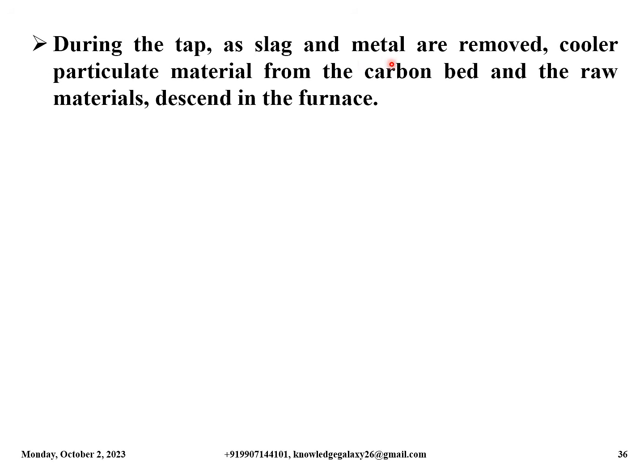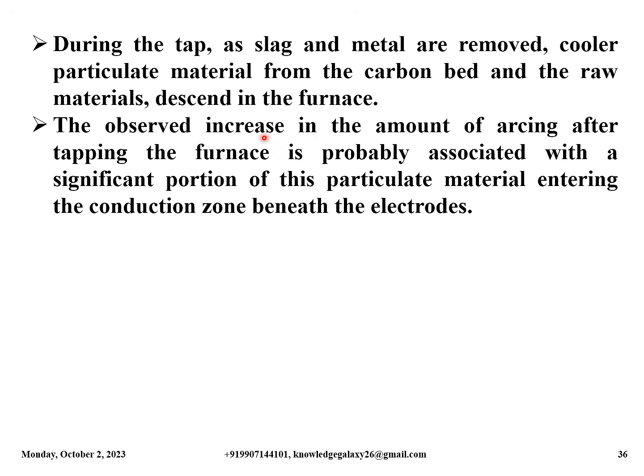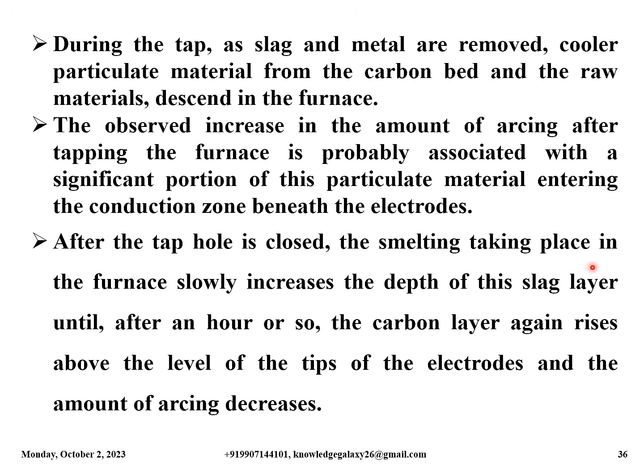During the tap, as slag and metal are removed, cooler particulate material from the carbon bed and the raw materials descend in the furnace. The observed increase in the amount of arcing after tapping the furnace is probably associated with a significant portion of this particulate material entering the conduction zone beneath the electrodes. After the tap hole is closed, the smelting taking place in the furnace slowly increases the depth of this slag layer, until after an hour or so, the carbon layer again rises above the level of the tips of the electrodes, and the amount of arcing decreases.